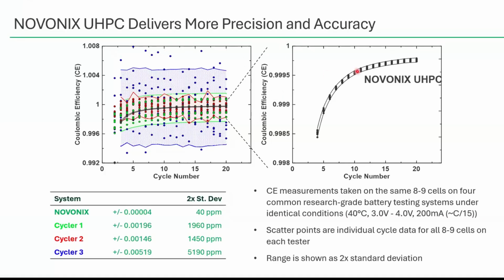We can really blow this up to see the spread of these cells on the NOVONIX UHPC system. What this really means is if we make a very small change to that cell's chemistry, to the electrolyte, to the cathode material, or even have a cell with slightly higher self-discharge than another cell - on the order of tens of ppm - we can actually measure that, identify it very early in a matter of just a cycle or two, and make really insightful conclusions or identify outliers.